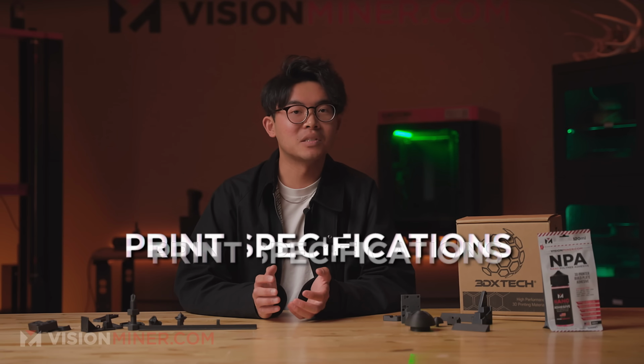When it comes to printing with CF PEEK, setting up your printer correctly is crucial. Here's what you need to know. Nozzle temperature: between 390 and 450 degrees Celsius. CF PEEK requires extremely high temperatures to properly melt and flow. This is because PEEK itself has a high melting point and the carbon fibers increase the thermal conductivity, requiring precise control. Bed temperature: between 70 and 140 degrees Celsius.